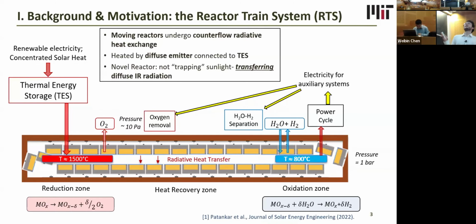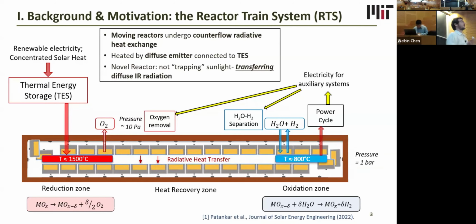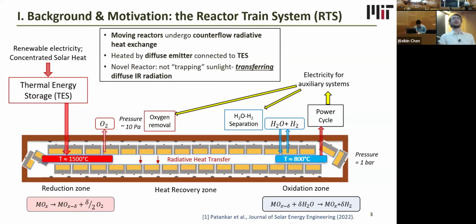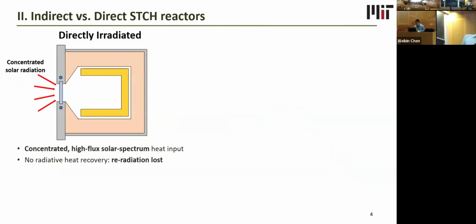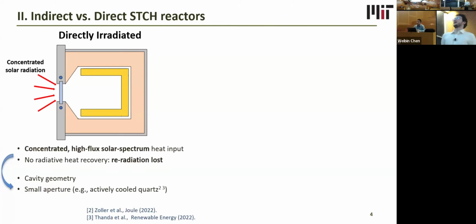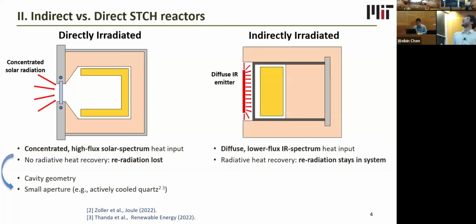This reactor needs to be designed not to trap sunlight, but instead to efficiently transfer infrared radiation. Let's look at what a directly irradiated reactor typically looks like. It uses concentrated high flux solar spectrum radiation to heat it, and it is not designed for radiative heat recovery, which means anything coming back out of the reactor is just lost to the environment. Therefore, it is designed to trap sunlight by using a cavity geometry and a small aperture, which is typically an actively cooled quartz window.